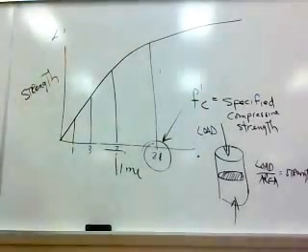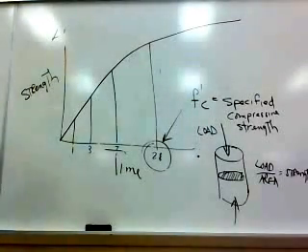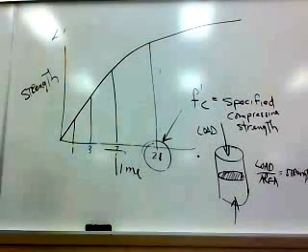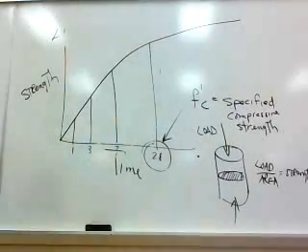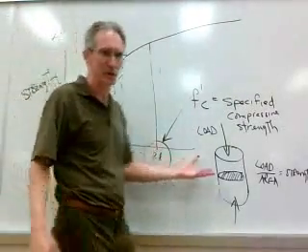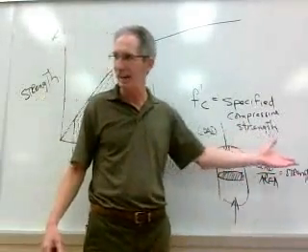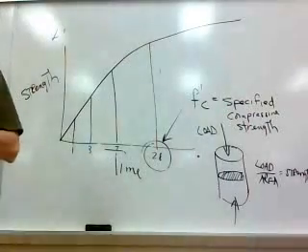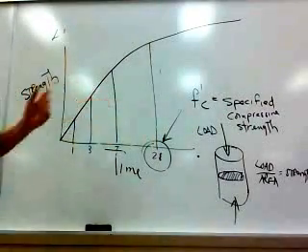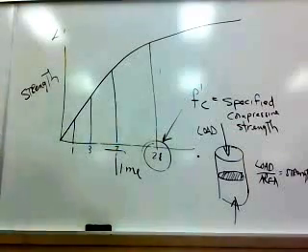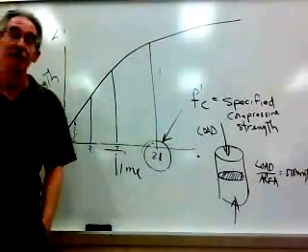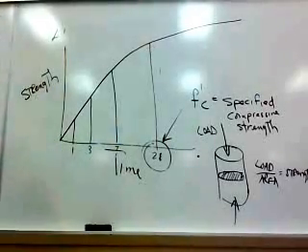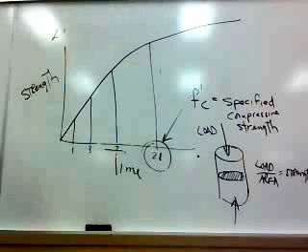Now again, if you really got into it, there are acceptance thresholds that the ACI, the American Concrete Institute, has for whether this is acceptable concrete or not. But in general, what we're doing is taking a look at our testing and comparing that to the specified value and saying, hey, does it work or not? The typical cylinder is a 6x12 cylinder, traditional, although they have adopted smaller cylinders for use. A 4x8 cylinder is a recognized alternative now.